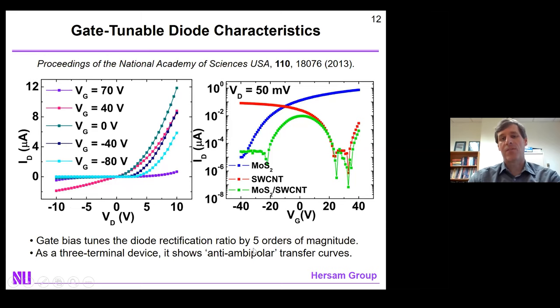From the perspective of a three-terminal IV curve, if you look at the drain current as a function of gate, you now see what we call an anti-ambipolar transfer curve, where the device is off at high negative or high positive voltage when you fully deplete the N or P side of the junction respectively. It's only on at low voltage. So this is the flipped over version of an ambipolar curve, hence the name anti-ambipolar.